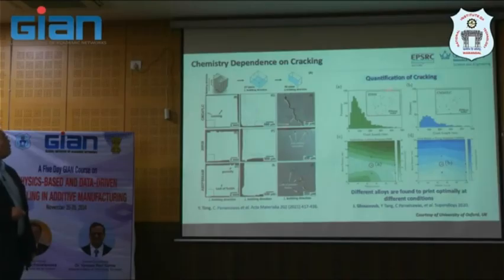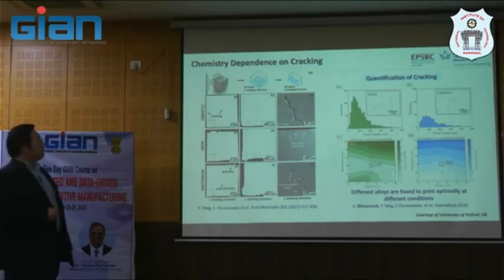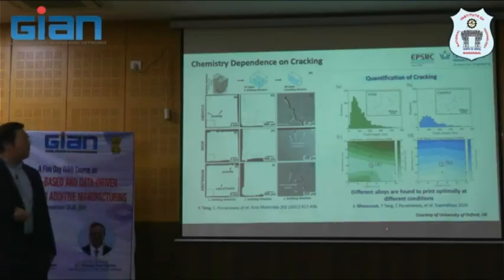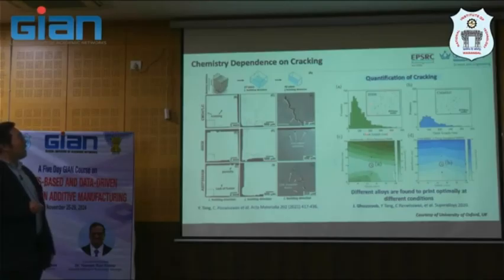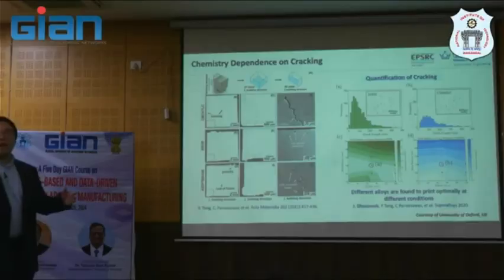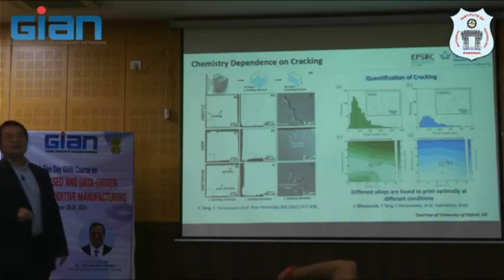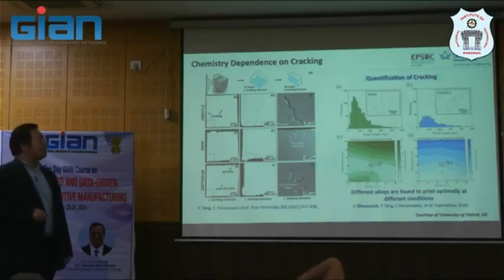But if you do some quantification of the cracking, you can plot the distribution. Joseph, our previous PhD, or DPhil, student, did very well: you can see the crack length from the images you take, and you will see that 939 has quite a lot of crack length compared in terms of distribution. And we summarize that the different alloys are found to print optimally at different conditions. Everyone knows this, but how can we have statistical evidence like this to prove how different? This is the question. It's not only about printing differently and cracking.